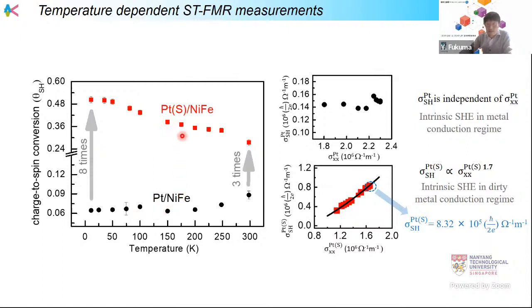This is a very interesting property. If the spin Hall effect is enhanced by an extrinsic mechanism, like skew scattering or side jump scattering, the spin Hall angle increases with decreasing conductivity. But this is a metal, so the conductivity increases with decreasing temperature. At the same time, with increasing conductivity, the spin Hall effect is enhanced for the sulfur implanted platinum. The enhancement mechanism is not clear so far. To understand the origin, we need to study it in more detail.